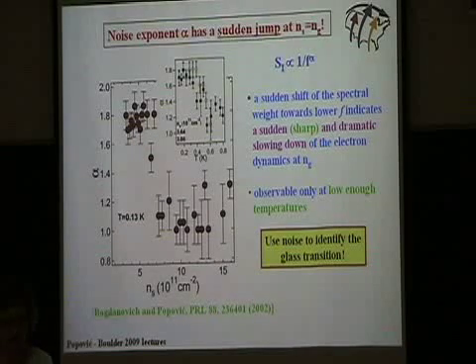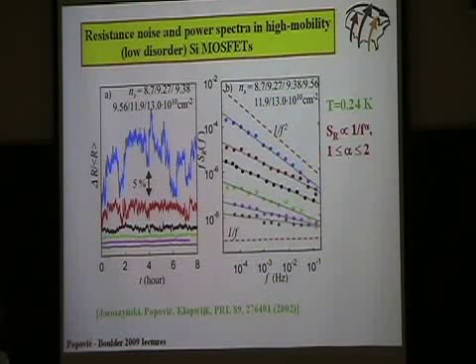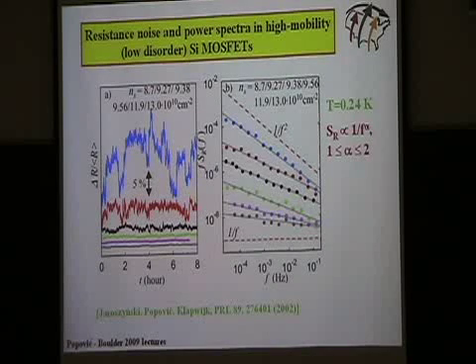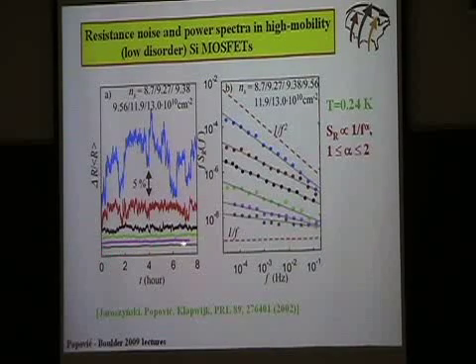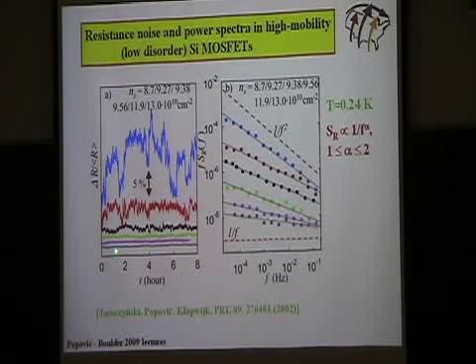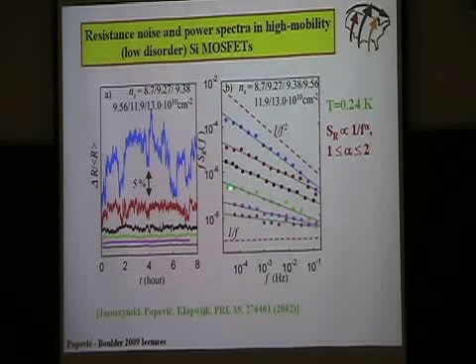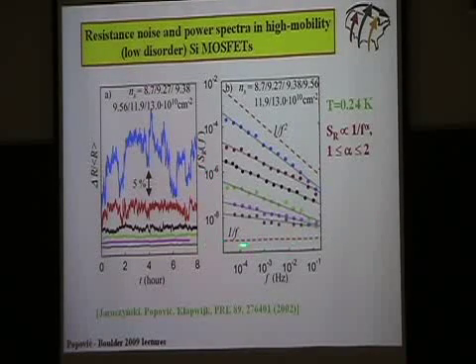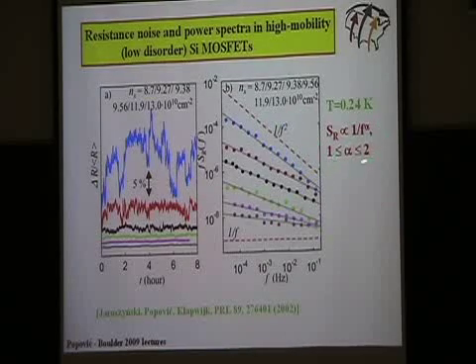So anyway, for high mobility samples, we use the noise to identify the glass transition, and here are some traces. It's similar to the other situation. High densities are here on the bottom. You can see that as you reduce the density, noise becomes bigger, becomes non-Gaussian. Then you look at the power spectra again. Here we multiply by F, so 1 over F is flat. So you can see immediately that the exponents are between 1 and 2.